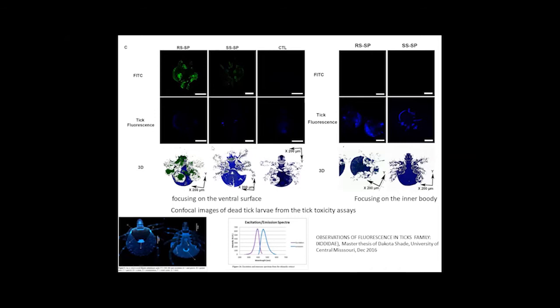When focusing on the inner body of the tick, in the images shown here, negligible green fluorescence was observed in both groups, indicating that the nanospinosad dominantly adheres on the outer surface, the body surface of the tick, rather than being ingested. This conclusion can also be confirmed by this 3D construction of the confocal image. This data is generated from the ANFF lab.